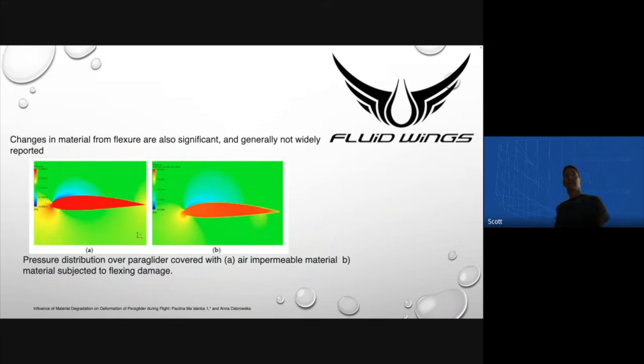They also did some modeling on what happens to the wing itself when the fabric loses strength and is worn from flexure. The important thing to note here is you can see on the left that's an impermeable material; this one doesn't have flexure damage and this one does. And you can see that lighter color over the front part of the wing looks like there's less intensity, right? So that's a lower pressure zone that's not as big, because that low pressure zone is your lift. And so the lift is not as strong and more diffuse, not as focused, right? And so the flexure changes actually reduce the lift capacity of your wing.